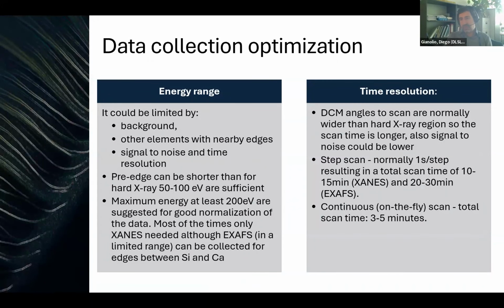Then moving towards the data acquisition and data analysis, of course, there are several parameters to optimize for the data collection to get a good quality of the data. One thing to take into account is that the energy range when you measure in tender X-rays could be much shorter than what users that are commonly using hard X-rays are used to. And this could be limited by changes in the background, by other edges from other elements in the same range. And in this case, there are a lot of edges if you are talking about L or M edges, and they are much closer to each other.